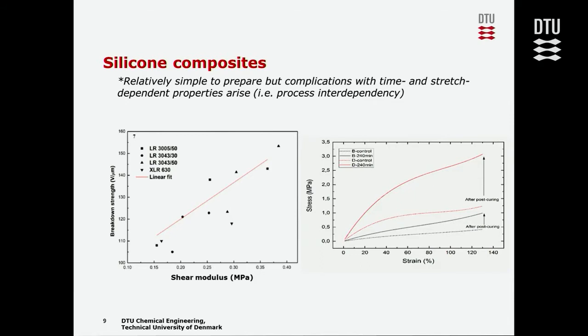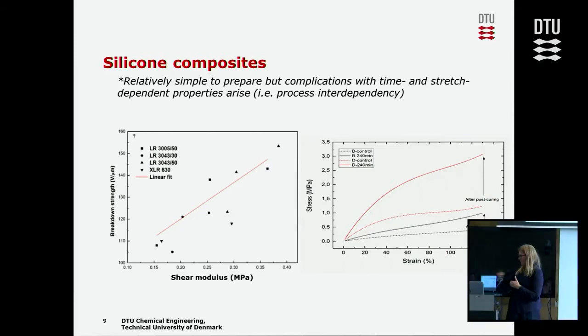And when we work with composites of the silicones, we enter into a lot of problems in the processing of the films, because we get a very high viscosity, and we need to add a lot of solvent in order to make it possible to cast the films. And then what we realized was that we really had to do a lot of extra work in order to be able to remove the solvent.